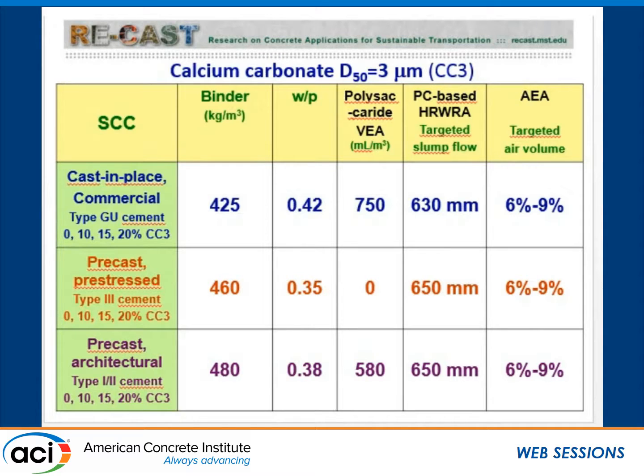The dosages were low. With the 0.42, we needed some. With the 0.35, we didn't need any. And with the 0.38, we needed a moderate dosage that was mainly added for robustness. And the slump flows were all, I would say, on the moderate side. This is 25, 26-inch slump flow, and all the mixtures were air-entrained.